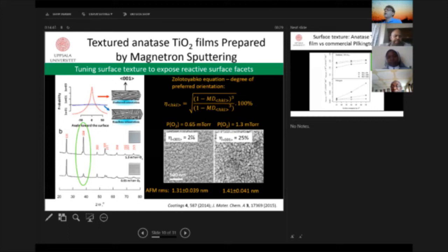Thank you. Forgive this interruption. There was a question online here, which I didn't really catch. But I continue. This is a busy slide with a lot of details, which I will not discuss. But the message here, if you start with the XRD pattern, is that depending on how you prepare it, you can get a larger fraction of 001 orientation of the films. And this can be tuned by reaction conditions, which I have explored in these publications. And this plot shows the probability that you have something other than a random structure. The red curve is a signal that you have something which is preferentially oriented. And this comes at an angle to the surface normal, if you do the calculations.